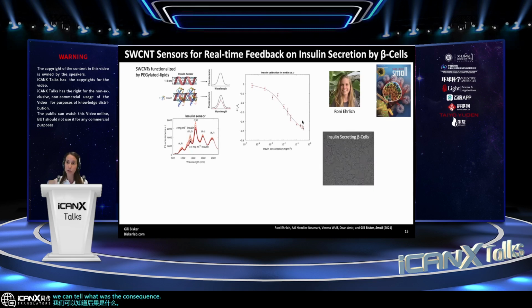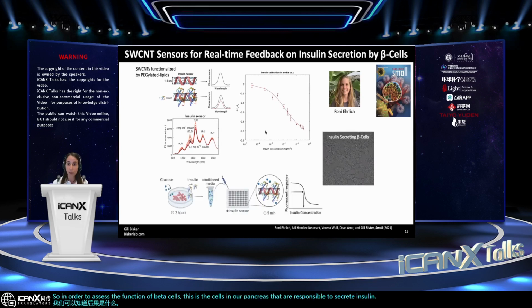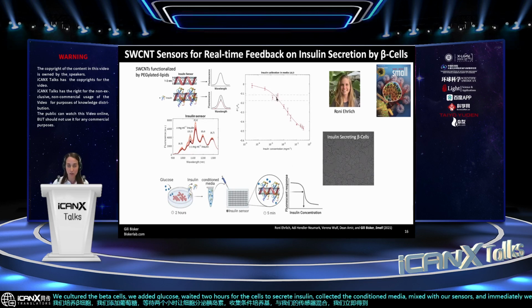So in order to assess the function of beta cells, these are the cells in our pancreas that are responsible to secrete insulin in response to glucose, we conducted the following experiment. We cultured the beta cells, we added glucose, waited 2 hours for the cells to secrete insulin, collected the conditioned media, mixed with our sensors, and immediately we get the fluorescent response from which we can deduce the concentration. And this is the result that we got.